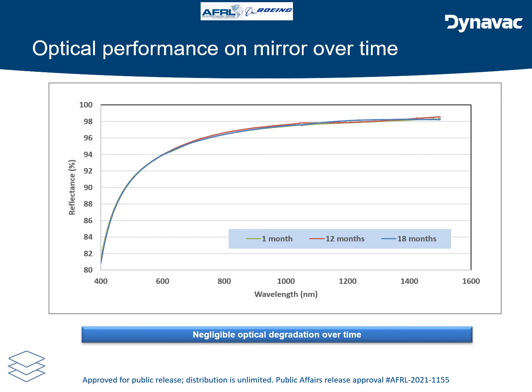Optical performance on mirror over time. We did have witness samples in the telescope, and we measured the reflectance over time. This plot shows the reflectance data over a period of 18 months. And as we can see here, it stayed put and there was no noticeable degradation over time, which is good news.